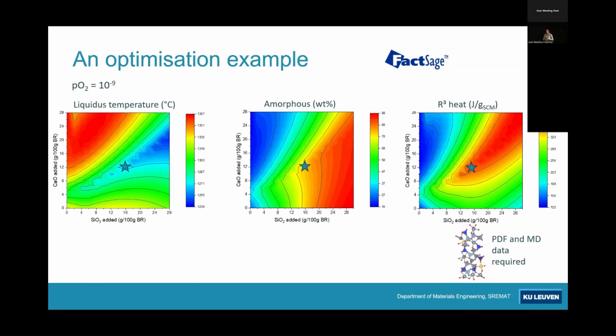We don't want 100% amorphous content because there are quite some heavy metals in the bauxite residue, chrome and vanadium, and we trap them in spinels. So we want some crystals, not too much because it will lower the activity, but it can help. And then the R3 heat, we could also predict that. We use molecular dynamics simulation data and PDF, pair distribution function data. It's a bit more complicated, but we could also get an idea of what the R3 heat is.